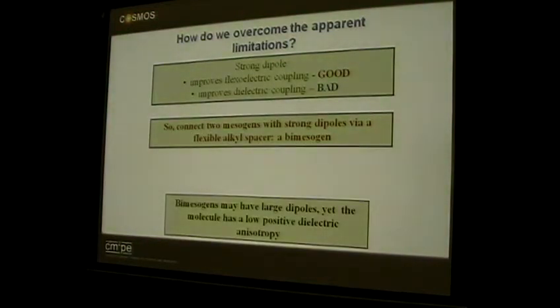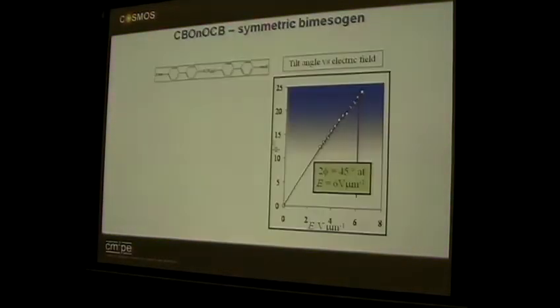Okay. They may have large dipoles, and you sit them end to end. So the dipoles sit out, and they self-cancel. But when the system bends, you generate polarization. Okay, so if you distort the director, if you distort the molecules, you generate polarization. And it's the bimesogens that are key to the effects I'm talking about.